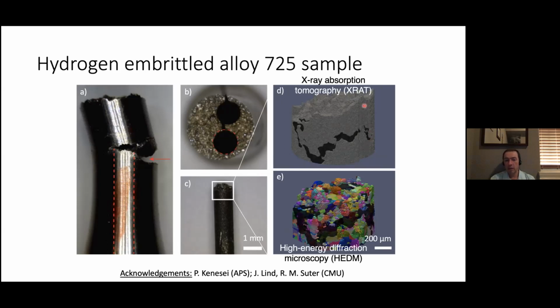At the same beamline, you can actually do X-ray absorption tomography, which is very nice because you need that to map out, if you're studying a specimen like the one that we had here that has this big internal crack, the shape of the crack. And then you can correlate these two 3D reconstructions. You can register them, put them into registry with each other, and then you can figure out what are the sizes and shapes and orientations of all the grains along the entire crack face in this sample. So this is a very powerful technique.